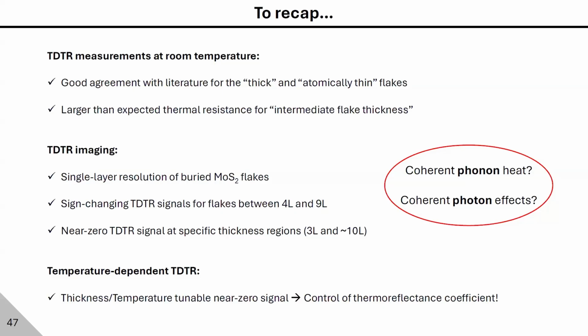We showed a sign-changing signal between flakes for flakes between 4 and 9 layers, and we show near zero TDTR signals at specific thickness regions of 3 layers and around 10 layers. We confirmed with temperature-dependent time-domain thermoreflectance measurements that specific thickness-temperature combinations would lead you to a control of the thermoreflectance coefficient. So you can either change the thickness or change the temperature to achieve zero thermoreflectance signal wherever you want in your sample. So we explained our results in terms of potential coherent phonon heat transport and in terms of coherent photon effects.